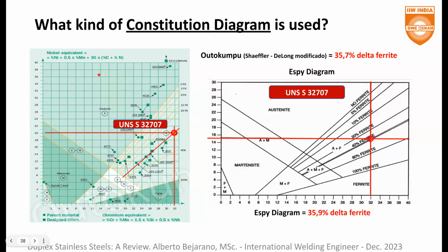We just calculate chromium equivalent and nickel equivalent, and there will be a point in which these two values cross, and based on the slope we calculate the amount of delta ferrite. Okay, very good.